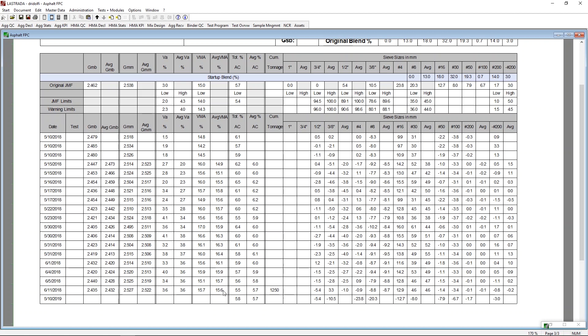So if we're trying to understand which sizes are affecting VMA, why don't we look for that same trend where we start low in a value, we trend our way up, and then we make our way back down. Now, when you look at the data, you see that same behavior in the number 8 screen. You can see roughly that we start to lose more and more of the number 8 material, and then we start to trend our way back down. And again, I went ahead and averaged the rolling average of 4 on the number 8 screen because the number 8 screen tends to be a very influential screen relative to VMA.